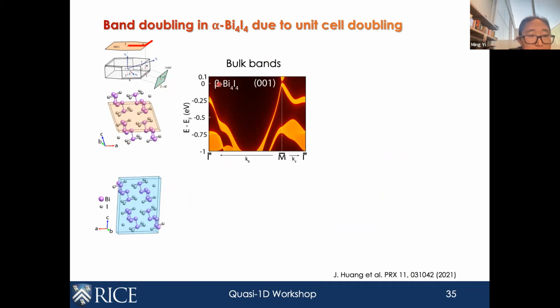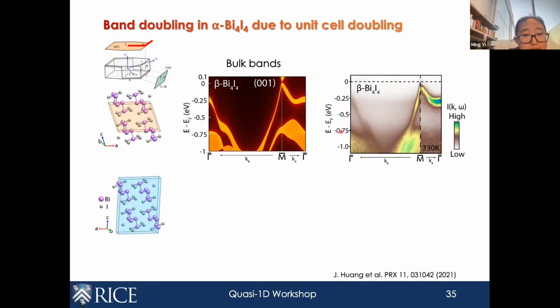This is the calculated kz-integrated bulk band dispersions for the beta phase. And you can see a side-by-side comparison with our measurements at 330 Kelvin, and they are basically a very good match between left and right. And this is because of the kz broadening that we have intrinsically in photoemission.